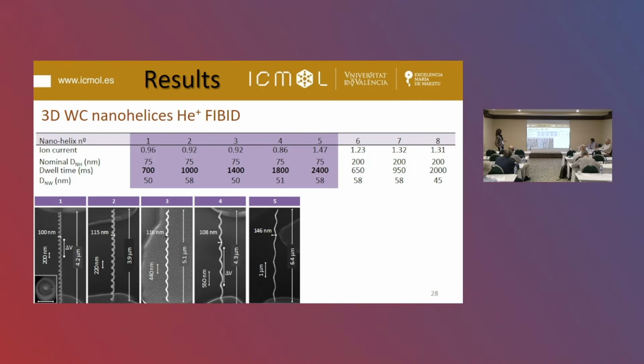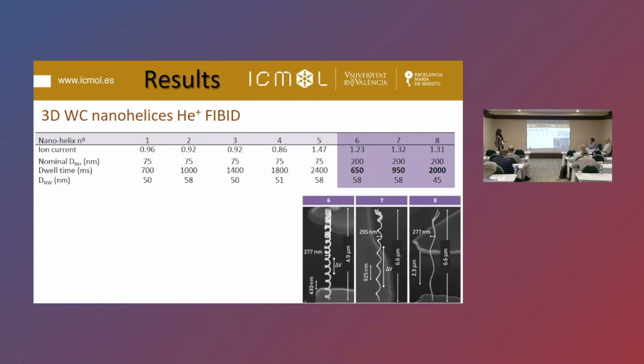I was trying to keep the diameter of the nanohelix constant at around 100 nanometers, and the turn length goes from 200 nanometers to 1 micron. In the other case, 200 or 300 nanometers in diameter, and the turn length goes from 400 nanometers to 2.3 microns. So it's possible to really tune the 3D geometry, the distance between each turn, and the nanohelix diameter as well. And the wire diameter of each nanohelix is around 50 nanometers.